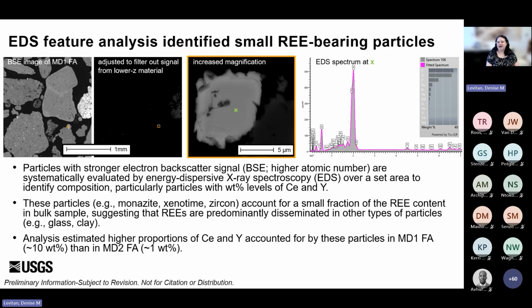So when we look at just regular backscatter, we see in this image different shades, some brighter, some duller, and that does reflect the composition. So if we change that threshold so that we're not looking at all of these different elements, but just the very brightest ones, we can filter out a lot of that aluminum and silicon and look for just the bright spots. You can't really see it in this, but there's a bright spot in this little square here, I can assure you. So then if we scan the sample for just those bright spots, we can then look at them more specifically for their composition with the EDS, which then tells us what those elements are, not just bright, but like yttrium.